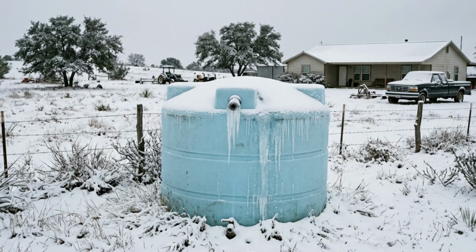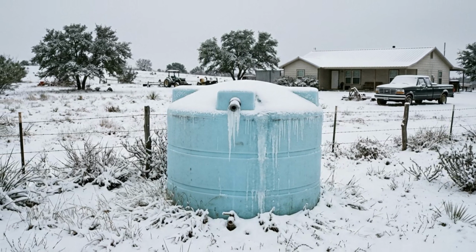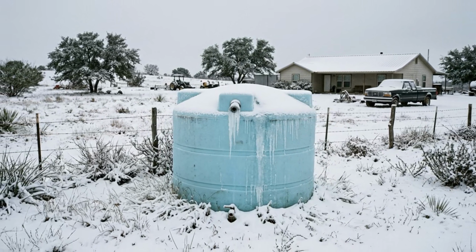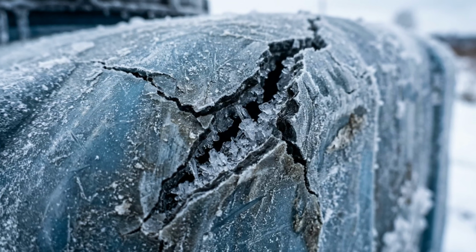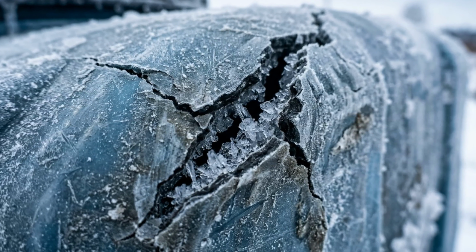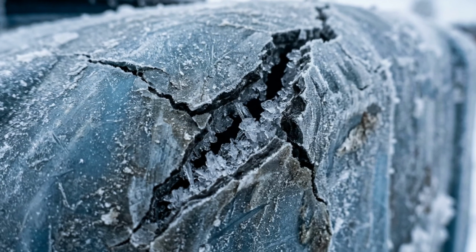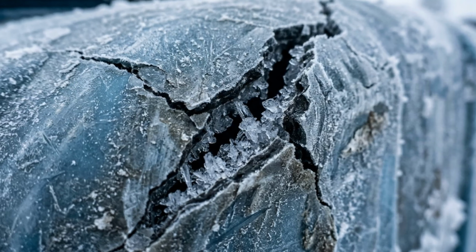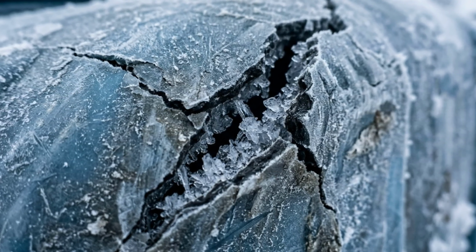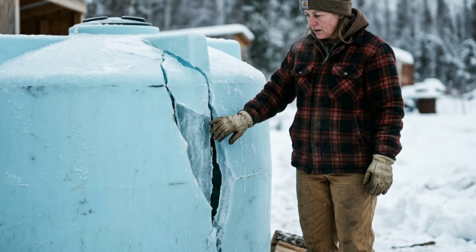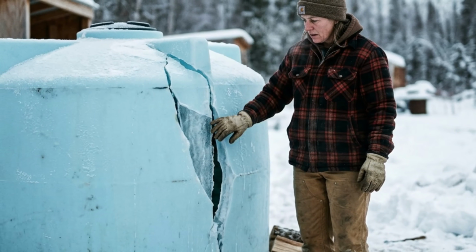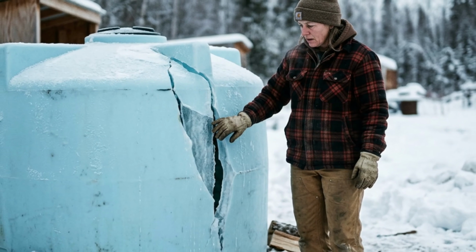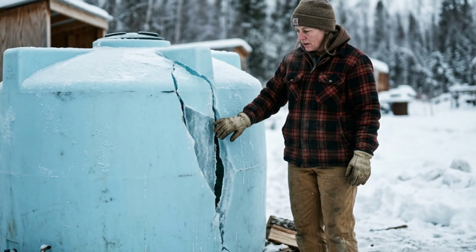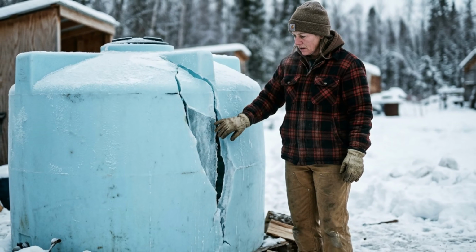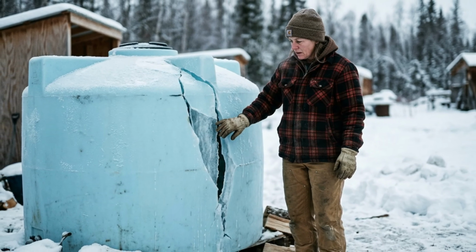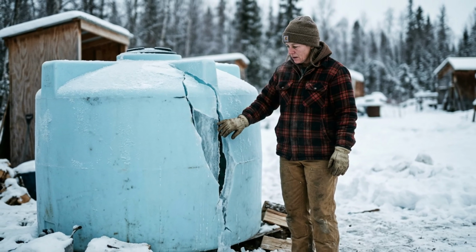The February 2021 Texas freeze demonstrated a second failure mode. Above-ground polyethylene tanks exposed to sustained below-freezing temperatures develop stress fractures as the water inside expands during freezing. Texas homesteaders reported widespread poly tank failures during that event, storage systems built for Texas climate that failed precisely during the crisis when water storage mattered most.